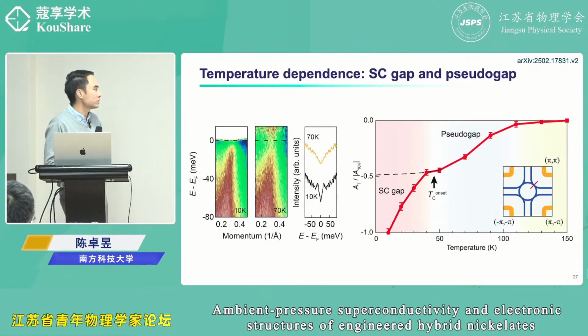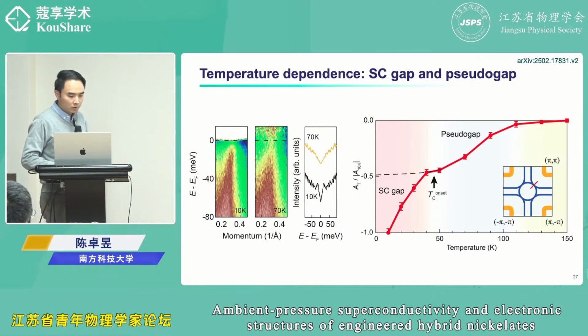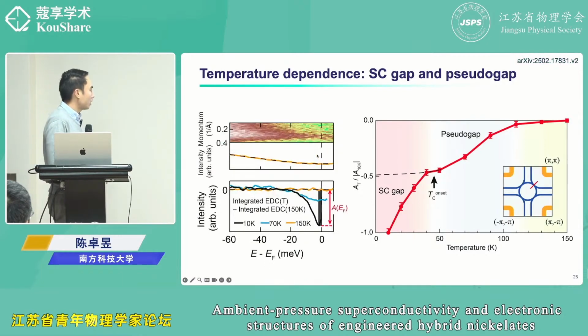Right. Temperature dependence. So this is the data we just saw at 10 Kelvin. You see a gap and also a coherence peak, and at the higher temperature you see some dip. It looks like a gap, but no coherence peak. To understand this quantitatively, we can measure the depth of the dip of the gap, and as a function of temperature it is plotted on the right.